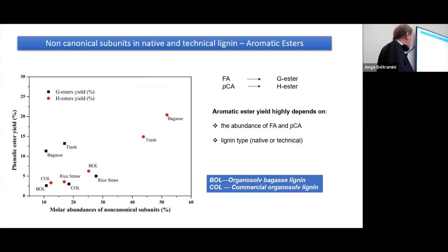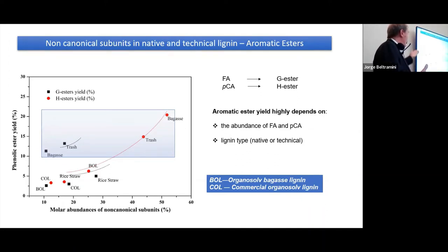What is important at the end of the day is that we confirm the production of the G and H ester, ferulic acid and coumaric acid, is higher with the bagasse and the trash. The phenolic concentration yields are larger than in the other variations of the lignin that we studied.